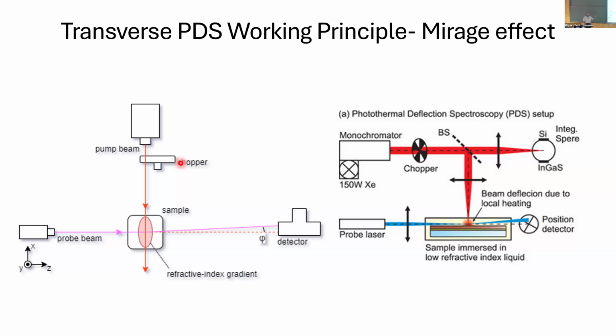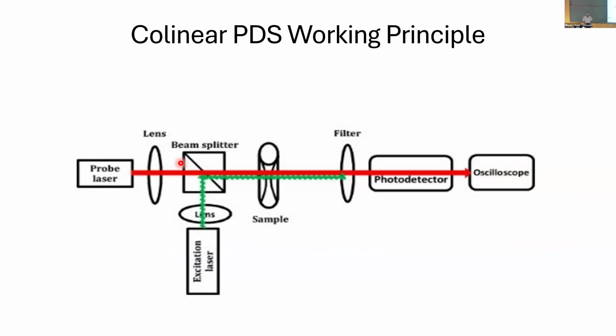But for that, this measurement doesn't work, the transverse measurement, because here the laser is going on top of my sample, and my sample, if it is liquid, has to be enclosed in some container, and my laser cannot go in at the edge of the container. It has to be closed. So now what I do is I flip the system and go into mode of PDS.